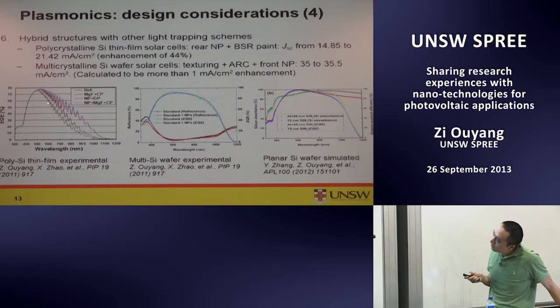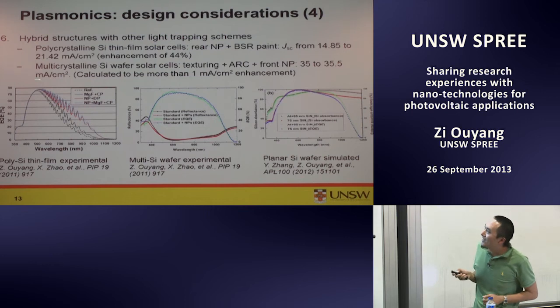So this is the nanoparticles put on the rear side with a back-surface reflective paint. What we get is this curve, the very high EQE boost, up to 44%. And this was the benchmark before we had the plasmonic work. Conventionally, this white paint, which is this black curve, was the benchmark of thin film solar cells for maybe 5 to 10 years. So we really boost quite a lot due to this technology.